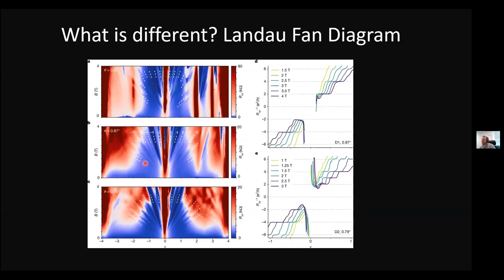What we believe is that spin-orbit coupling also plays a role, if you look at the Landau fan diagram of these devices. We see a more prominent twofold symmetry, meaning that some of the original fourfold symmetry around charge neutrality is now broken into twofold symmetry, which you would expect from spin-orbit coupling. So we see these filling factors of 2, 4, 6, 8, 10, and even at really small fields you can see quantized conductance steps in Rxy. Occasionally, we see the odd steps as well. So it's a combination of interactions and maybe spin-orbit coupling that plays a role in defining the physics of the Landau fan diagram around charge neutrality.